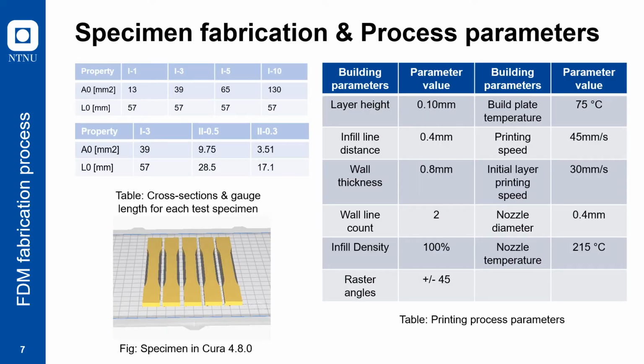These are some of the process parameters we used for the fabrication. For the thickness effect, as you can see from the table at the left top corner here, we have determined four thicknesses, which are 1 millimeter, 3 millimeter, 5 millimeter, and 10 millimeter. And the second table below is for the scale effect. So the largest scale is the one same as the 3 millimeter specimen, and then we scale it down to 50% and 30%, and the rest of the numbers indicate the cross-sectional area and the gauge length for each test specimen.